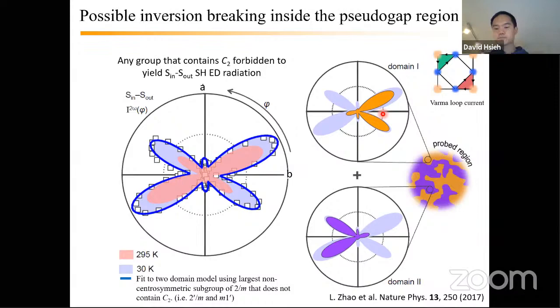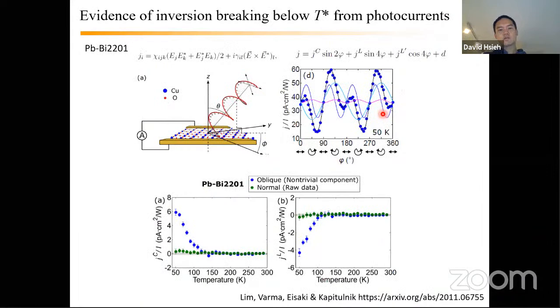I do want to mention briefly that there was a paper that appeared online a few days ago from the Kapitulnik group at Stanford, using also a second order nonlinear optical technique, this time not second harmonic generation, but rather optical rectification, where you have two electric fields, electric field omega times electric field minus omega, giving rise to a DC response, which you pick up as a DC photocurrent. Okay, so here instead of P equals chi E E, it's really J equals chi E E star.